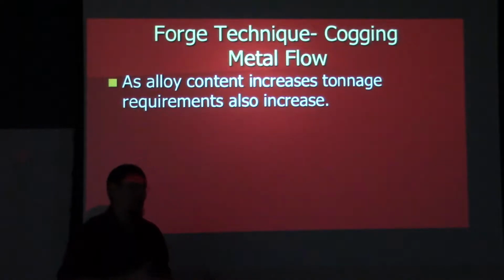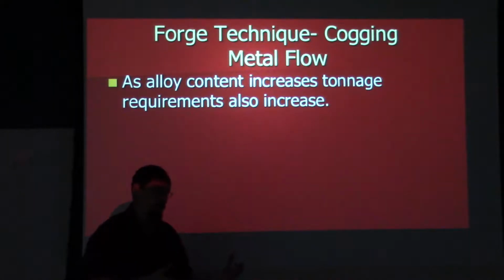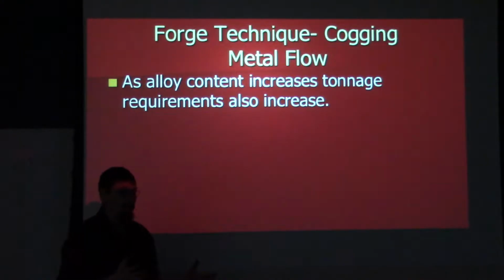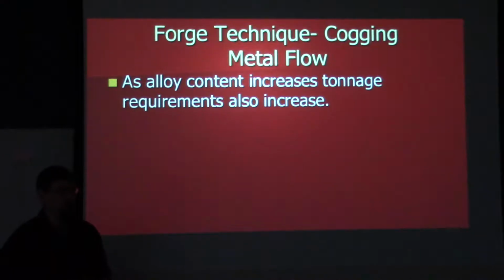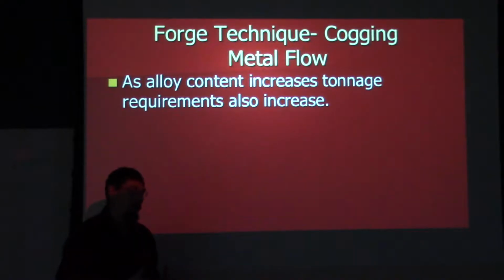The trade-off is that you have to stay at that temperature range or the iron silicate starts to solidify, and now it's not easy to deform, and then it wants to crack and crumble and be difficult to work with. Wrought iron was available in different grades that were based on how much iron silicate was in them, and so the lower iron silicate versions were easier to work with. You had a wider window.